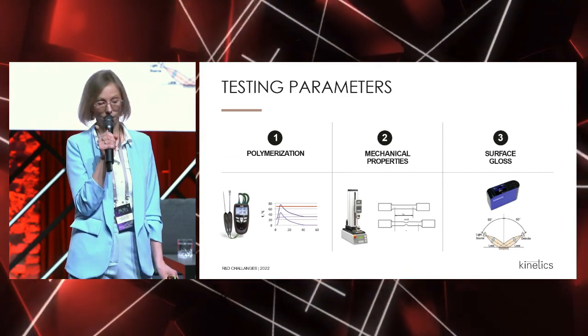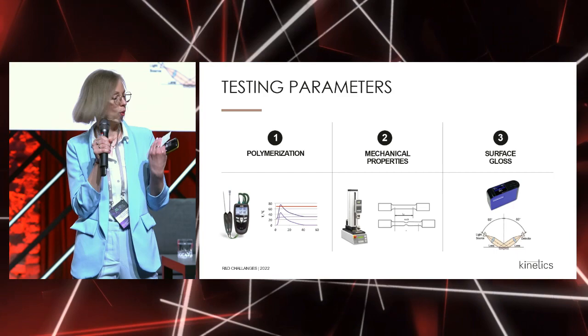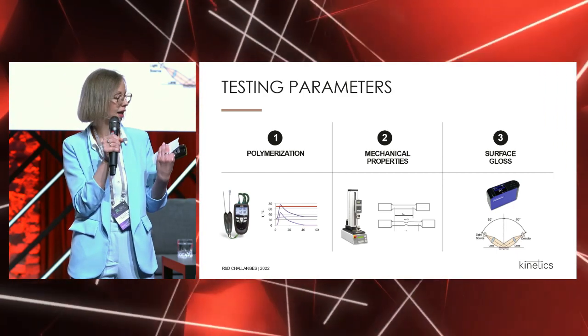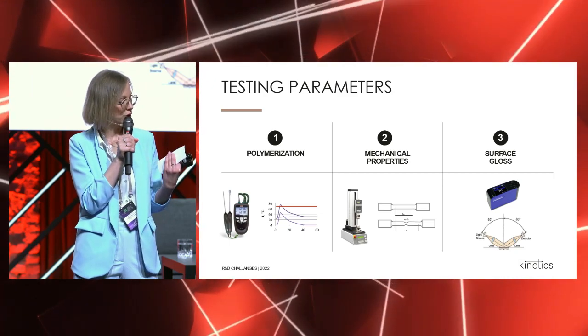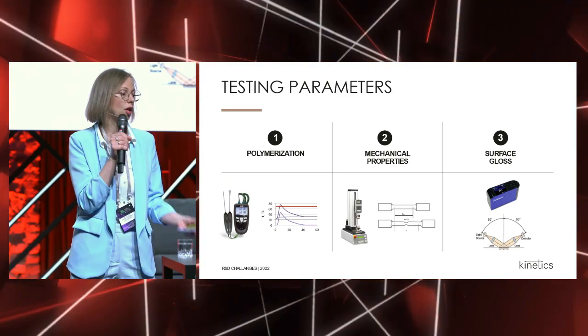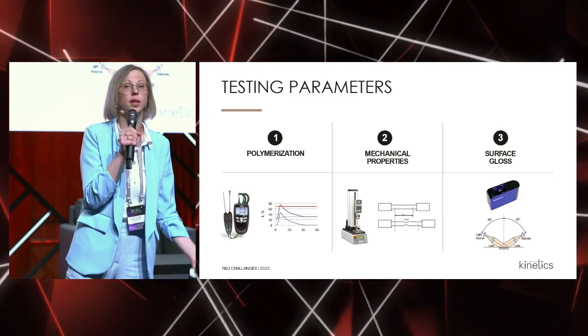And surface gloss. All of us want nice, shiny nails, and we should keep this shine not only right after the polymerization, but also over a 3-week period. And there comes one more story: usually we really wait for 3 weeks. We wear the gel polish on nails and look after 3 weeks how the gloss performs. But waiting 3 weeks for one parameter was too long for us.